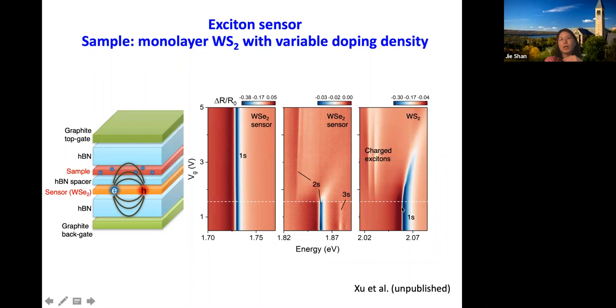Below, it's insulating, the Fermi energy is in the gap. And as soon as you introduce charge, in this case electrons, into the WS2 layer, the neutral exciton loses its oscillator strength and blueshifts, as you heard in Imamoglu's talk, as the repulsive polaron. At the same time, another redshifted branch appears, and this is the attractive polaron, and sometimes we call it a trion or charged exciton. So this is pretty well known for an isolated monolayer.